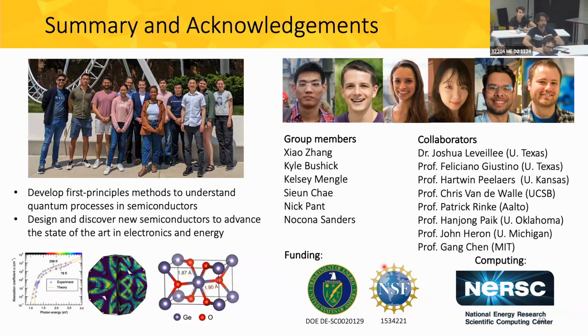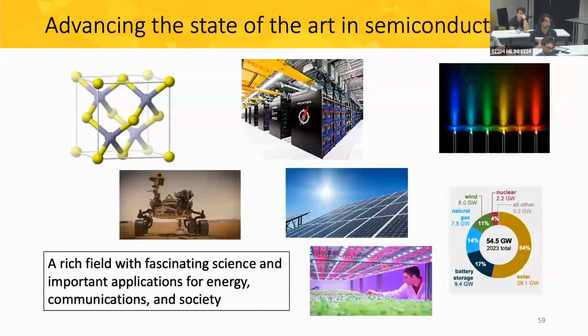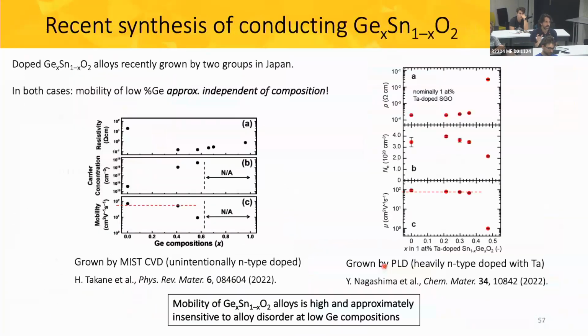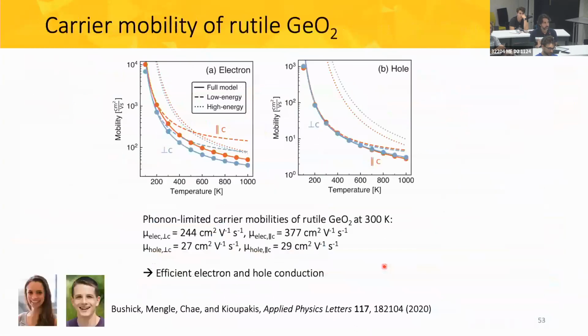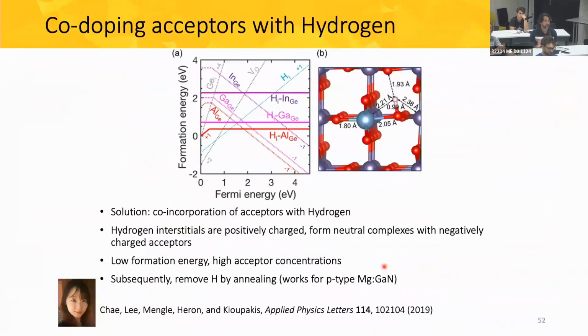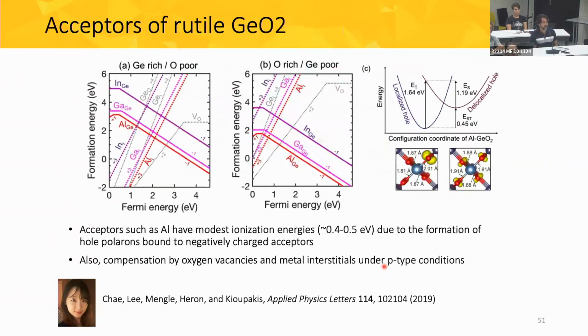Hi, Manu. Thank you very much. Very nice presentation. For the case of magnesium in gallium nitride, the activation rate is quite poor, about 1%. So when we want to p-dope gallium nitride, we need to dope quite a lot to get the acceptors that we want. And that in the end degrades the mobility and so on. So the p-GaN is really poor. What do you think will be the activation rate for germanium oxide?